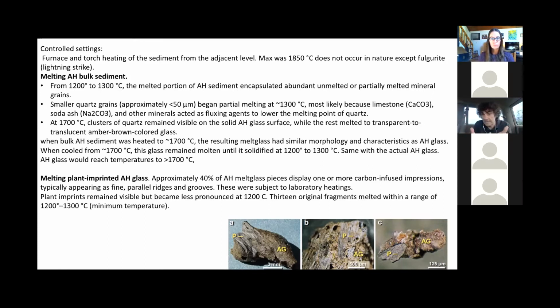So this is a similar way of how we think about it: a very fine molten material was hitting the surface organics and created these molds, shown here on this figure by P, which is plant material, and there's Abu Hureyra glass. We also did some melting to try to figure out the temperature at which this specific mold disappeared, which was about 1200 to 1300.